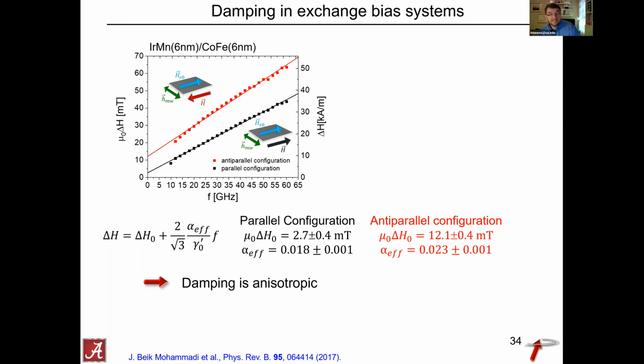And that's something, it's not that we haven't tried. The problem there is, in order to get it perpendicular, you typically need some adjacent layers that tend to really broaden the lines of those thin films. So it's a tricky experiment. Yeah, thank you. I think it's interesting to have a perpendicular exchange bias. They look at the possible argument about the two-magnon scattering. Exactly. That would immediately eliminate the argument about the two-magnon scattering.